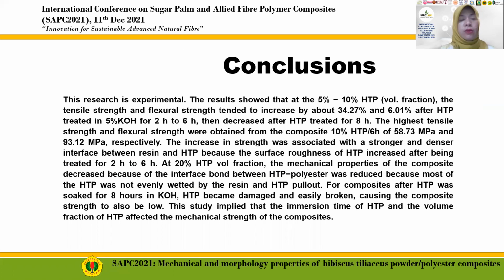Ladies and gentlemen, in concluding the discussion, we can note that at the 5% to 10% powder volume fraction, the tensile strength and flexural strength tended to increase by about 34.27% and 6.01% after the powder was treated in 5% KOH for 2 hours to 6 hours, then decreased after the powder was treated for 8 hours. The highest tensile strength and flexural strength were obtained from the 10% composite treated for 6 hours: 58.73 megapascal and 93 megapascal respectively.